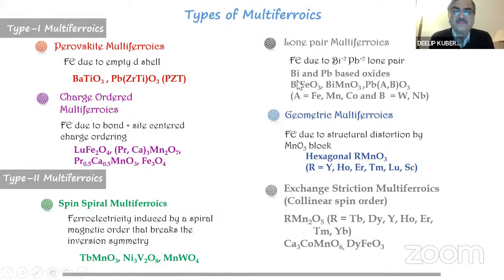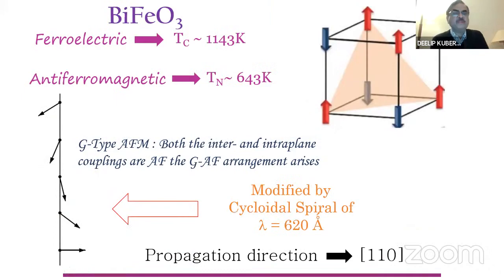So with this, we tried a lot, and I'm talking about almost 10 years before. Now it is highly stabilized. Everything is very clear, but we tried 10 to 12 years before, and we could successfully synthesize very good quality BiFeO3. So BiFeO3 has a ferroelectric transition temperature of 1143 Kelvin and an antiferromagnetic transition temperature of 643 Kelvin, which is quite high as compared to room temperature, and therefore its applicability is quite interesting,